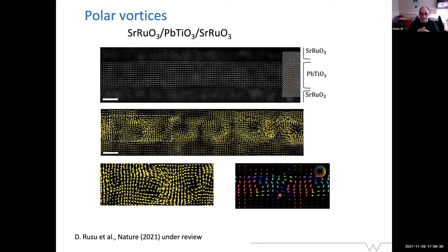Dorin runs pretty good DFT calculations, which gave us the initial hint that we should look into this strontium ruthenate, because that will allow the polarization to swirl. Nevertheless, the arrangement of the vortices here is not that nice. That was a little bit unexpected, because there is a periodicity, but it is not as nice as in lead titanate.